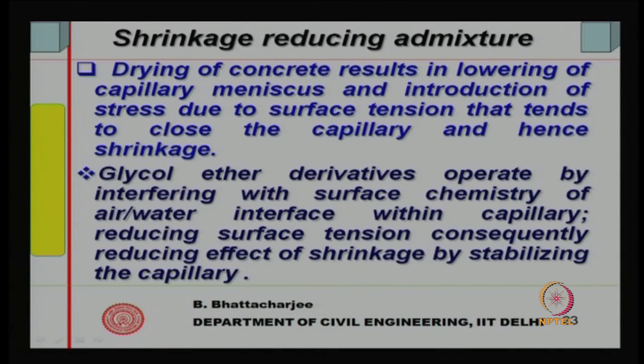Then there are shrinkage reducing admixtures. You see, drying of concrete results in lowering of the capillary meniscus, and since the capillary meniscus will lower, stress is introduced due to surface tension forces. These forces would tend to introduce a kind of stress at the capillary boundaries, because it was at a balanced condition, and now it has been lowered because some drying has occurred. There will be surface tension forces that tend to close the capillary and hence shrinkage. So, the capillary will try to collapse under these forces. Then of course, gel pores will also become empty. The water will move out from the gel pores subsequently, and there is shrinkage of the paste and hence of the concrete.